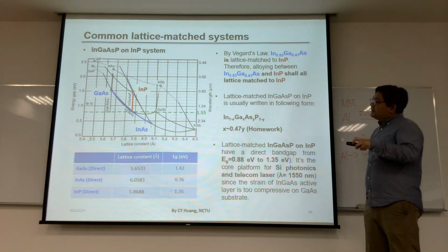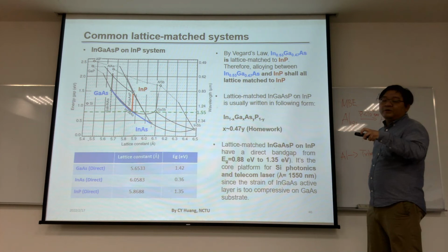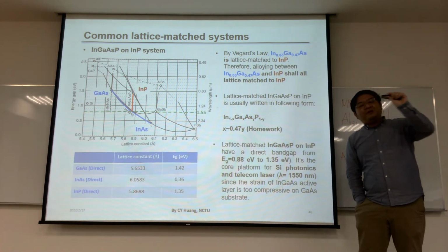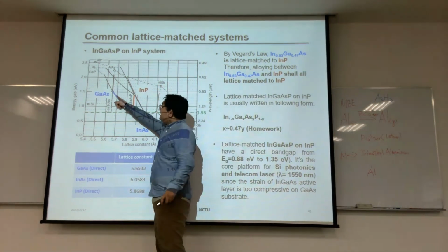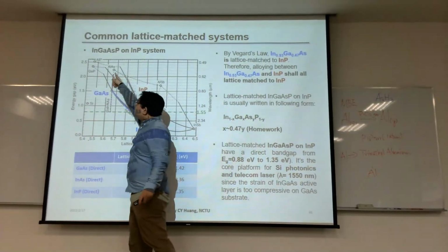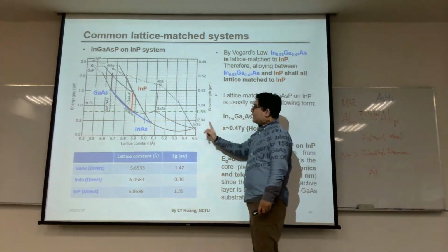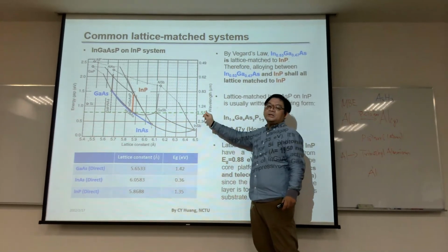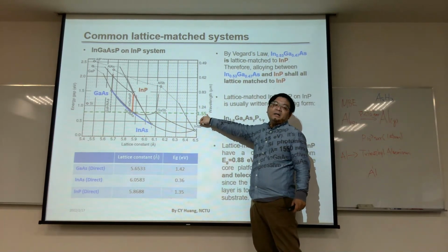The other issue is that with indium more than 20%, it's even difficult to grow a very thin quantum well in your crystal. So if you want an active region with an even longer wavelength, the GaAs-based InGaAs system is also difficult. So what should we do? For example, if we want a laser or LED at 1.5 micron.